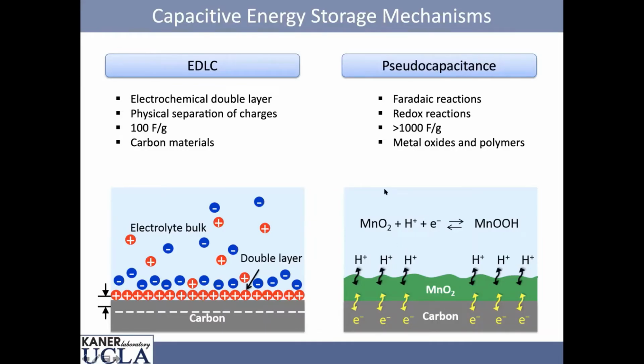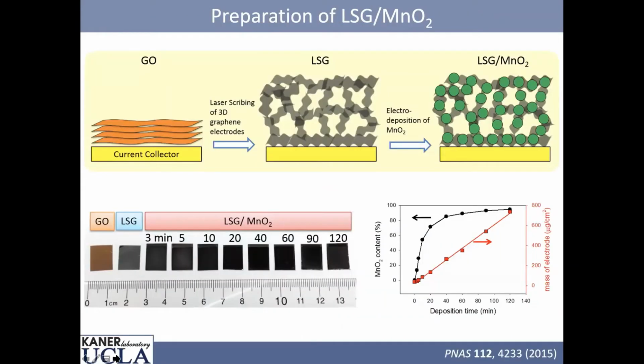And the carbon black is not electrochemically active. So our idea is to replace it with graphene. MnO2 by itself has over 1,000 farads per gram. You just can't get that. So what we wanted to do is put our graphite oxide and put the manganese dioxide in our laser-scribed graphene. We can do this electrochemically, we can do it chemically, and depending on how we do it, we can control the amount that we put in.